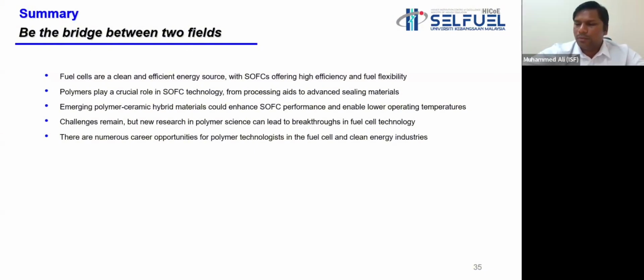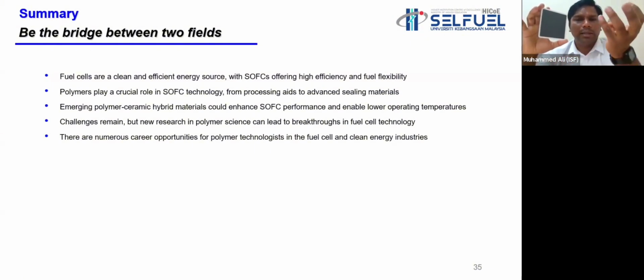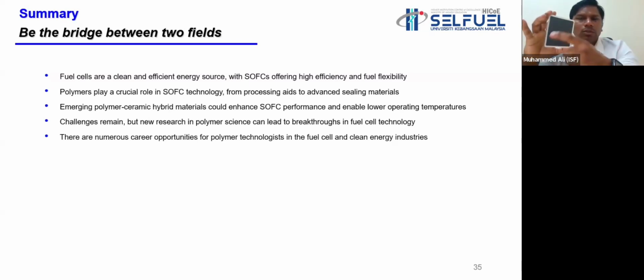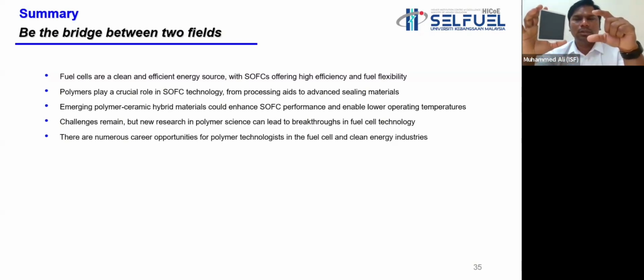Yes, when I showed you, this is the fuel cell, right? So this anode or cathode is being coated using screen printing or tape casting. This particular cathode material constitutes 60 to 65% solid content, whereas 35% constitutes the binders or plasticizers, surfactants, and solvents. So the combination of these 35% is very, very important.